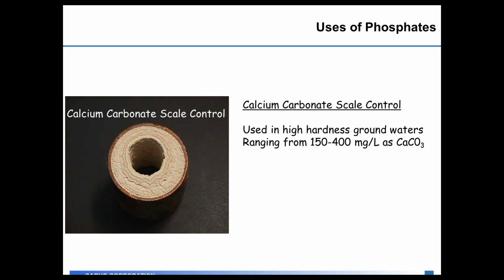Calcium carbonate scale control, like I talked about that picture earlier, the higher the hardness of the water, the higher your pH, you have a tendency for calcium carbonate scale to precipitate out of solution. As you get above 150 milligrams per liter as calcium carbonate up into the 200, 300, and 400 milligram per liter range, calcium carbonate scale will tend to build on itself and start restricting the pipe. This can also impact water meters as it plugs up the small parts in the water meter and you don't get accurate readings on what's being used water-wise in the distribution system. The phosphate will sequester the calcium carbonate and prevent it from precipitating out of solution so you don't restrict those pipes and water meters in the distribution system.